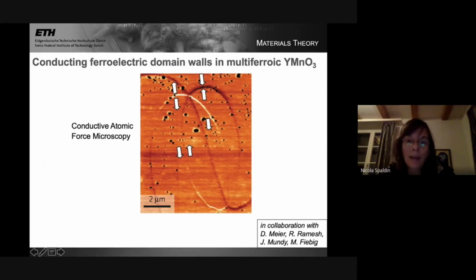And with the white arrows, I've marked the direction of the ferroelectric polarization. So here we have a tail-to-tail wall, so it's negative meeting negative, and here we have a head-to-head wall, so it's positive meeting positive. And the yttrium manganite is natively p-type, so it has a lot of free positively charged holes drifting around in the material, and these accumulate at the tail-to-tail walls to screen the negatively charged ends of the dipoles. At the head-to-head walls, where there needs to be negative charge, the conductivity is lower.